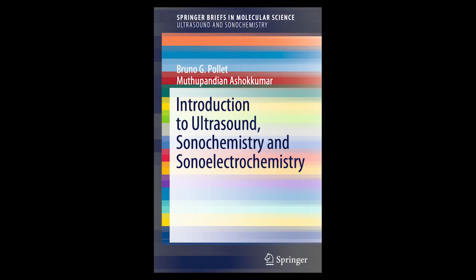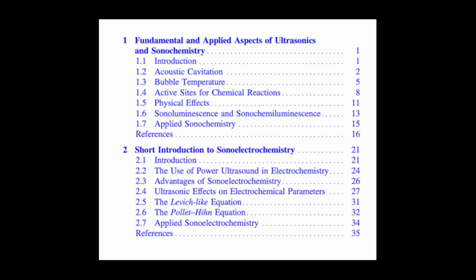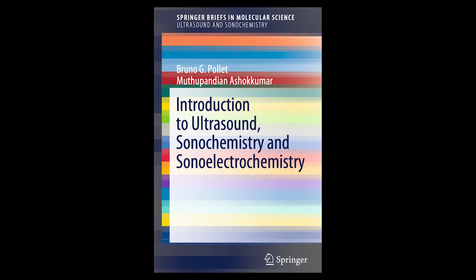Now this is where things get a bit more nuanced, and the literature actually shows some conflicting results. It's not as clear-cut as the mass transport effect. What are the different findings? Well, some studies have reported an increase in the intrinsic rate constant k naught under ultrasonication. What's the explanation for that? Faster chemistry. The usual explanation is the localized heating effect.